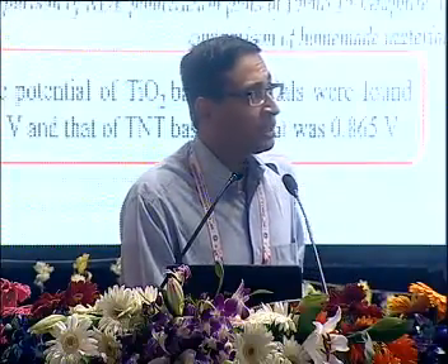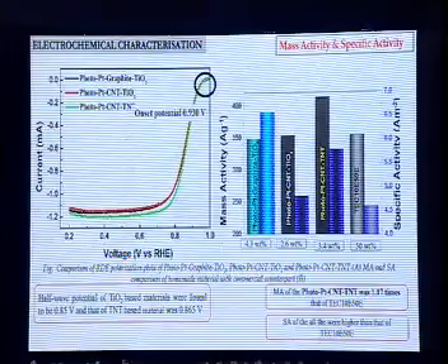And finally, summarizing the overall effectiveness of this method and the electrocatalyst, we see various other quantitative measures to prove that the catalyst is good and workable as an electrocatalyst. We see that the graphite-based electrocatalyst is on par with or a little more than the commercial catalyst with 58% platinum. And the CNT-based catalyst is far higher and is almost touching the range which the DOE, or the Department of Energy, has projected.